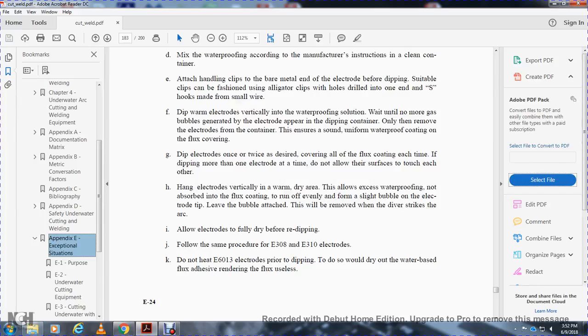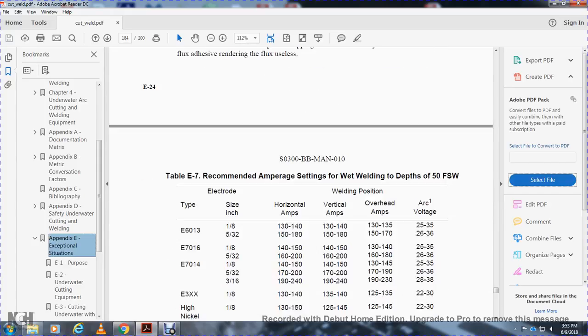Allow the electrode to fully dry before re-dipping. Follow the same procedure with the E308 and the E310 electrodes. Do not heat the E6013 electrodes prior to dipping. Doing so will dry out the water-based flux adhesive, rendering the flux useless.